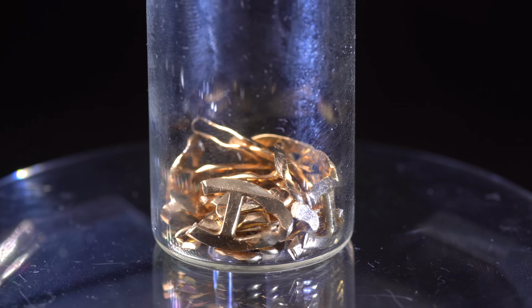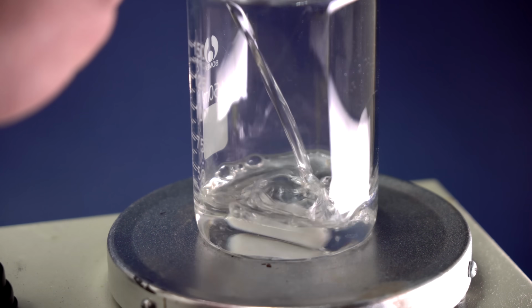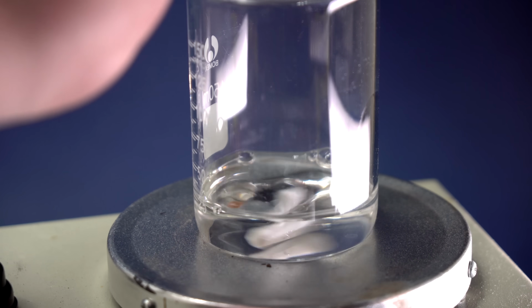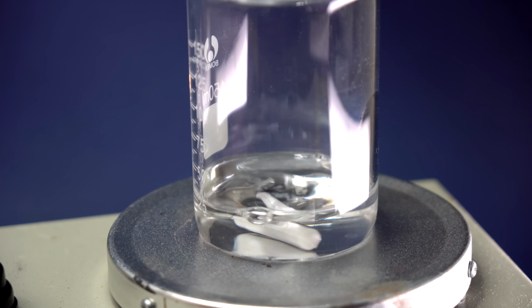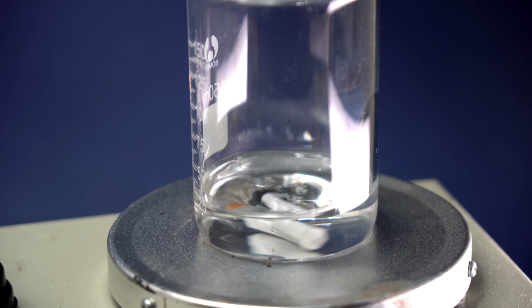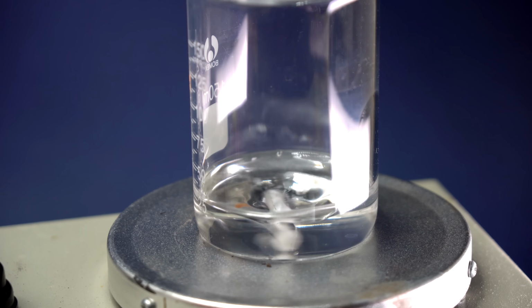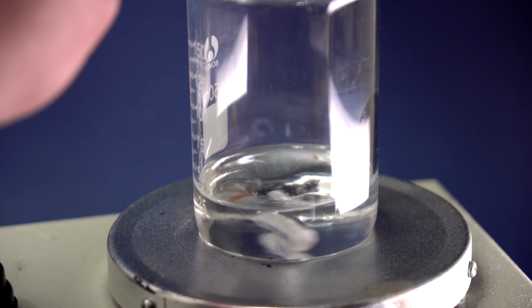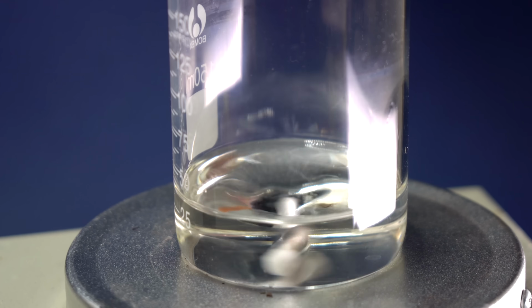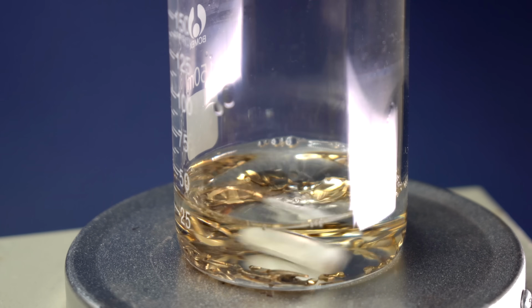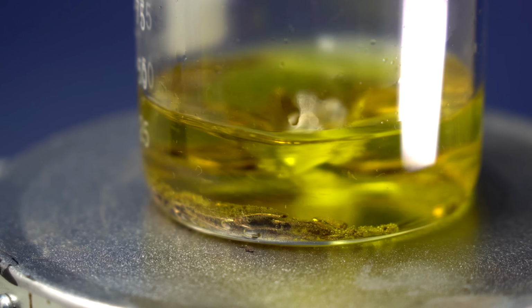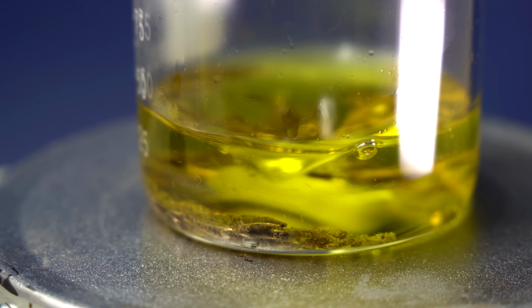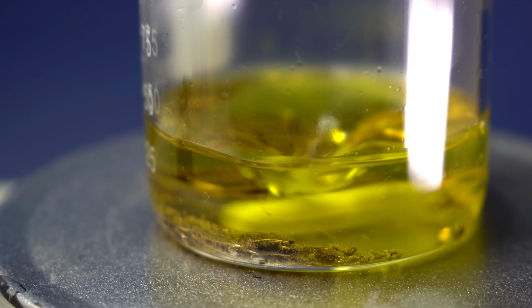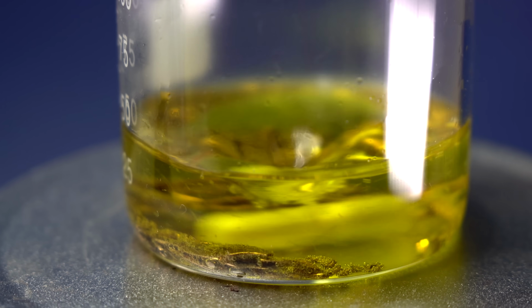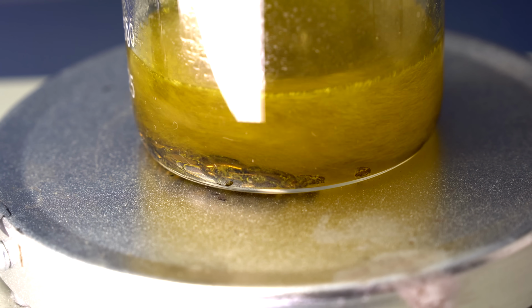That's quite simple. First, I'm preparing a mixture of 30 ml of 35% hydrochloric acid and 10 ml of 65% nitric acid, which is also called aqua regia. After making the mixture, I am immersing my gold bracelet chains in this solution. Upon being heated up, the alloy of gold, silver and copper actively starts to dissolve in the aqua regia.